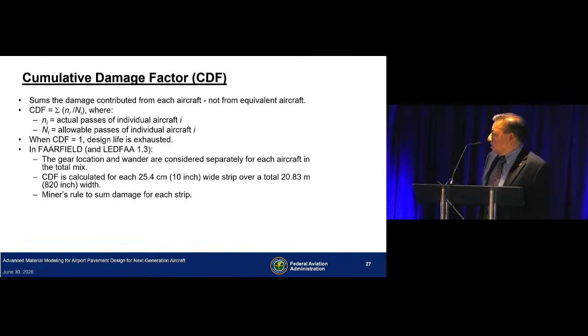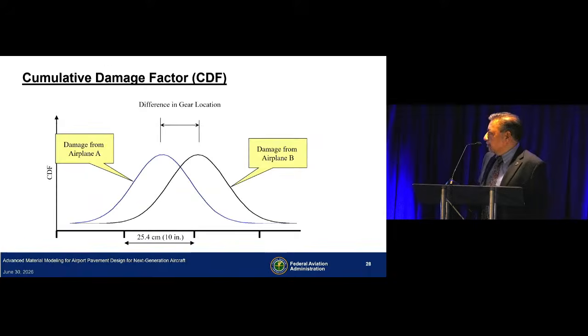So that is considered. And the CDF is calculated for each 10-inch wide strip over a total 20.8 meter width. That's where we compute for each 10-inch strip. We look at where the critical location is, and the CDF coming from each aircraft at that location is summed up to design your pavement. We use Miner's hypothesis to sum up the damage.